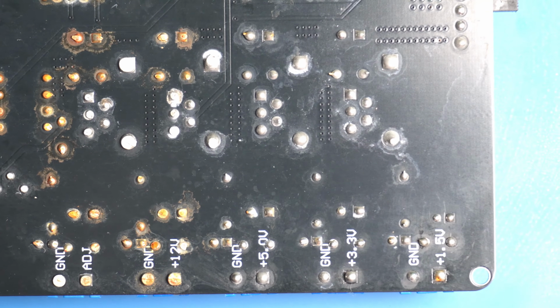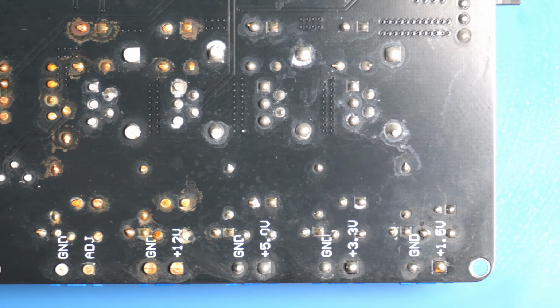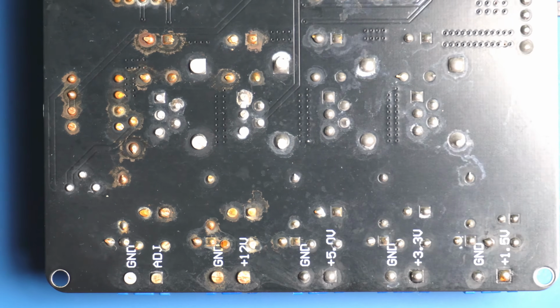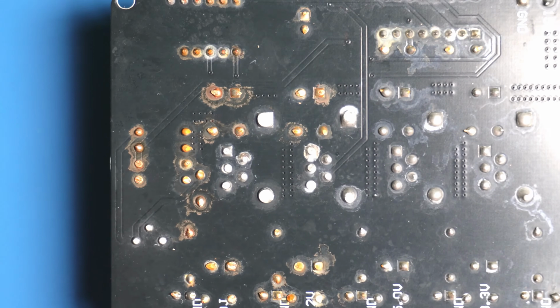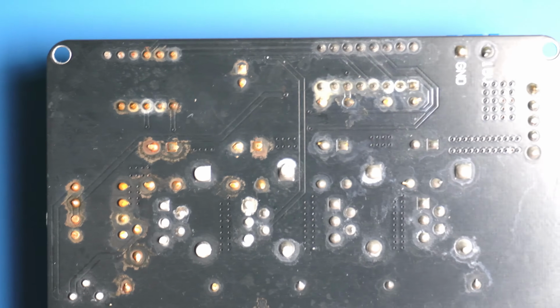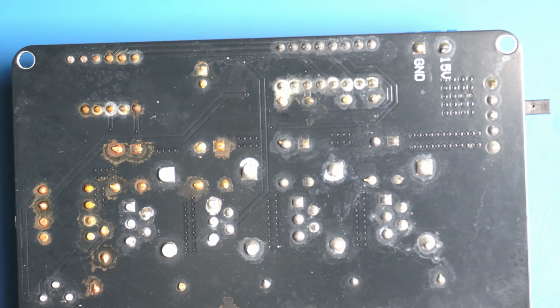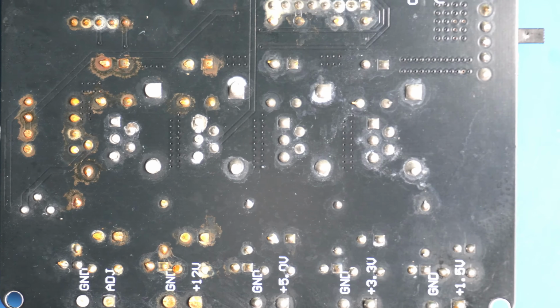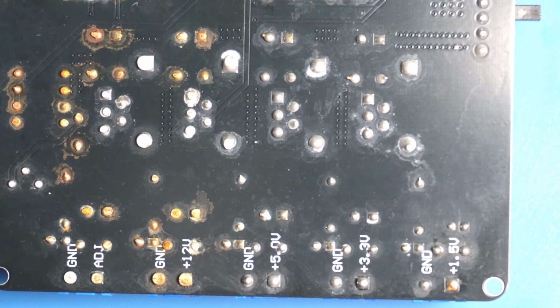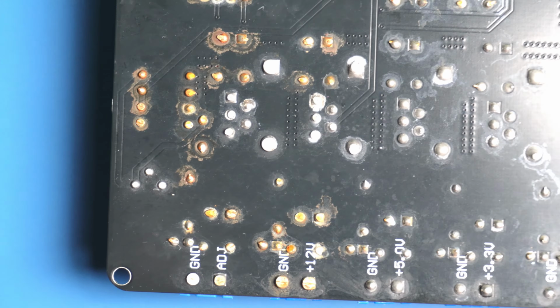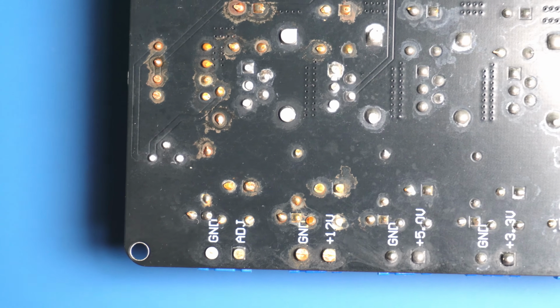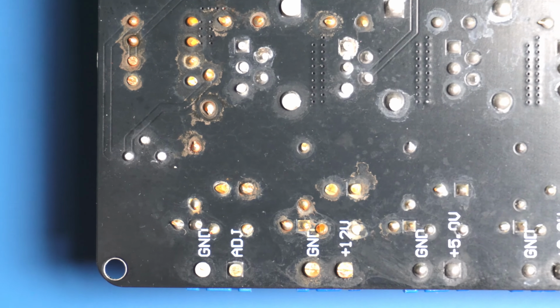After soldering, I cut all the leads, exposing the base metals. After the salt water test, the leads that contained iron or iron-based alloys in their core were covered in rust, but not all of them. The leads that don't contain iron alloys remain free from corrosion. DIP component lead metals are typically copper, aluminum, steel, brass, bronze or iron-nickel alloy. Guessing which one you have can be quite challenging.